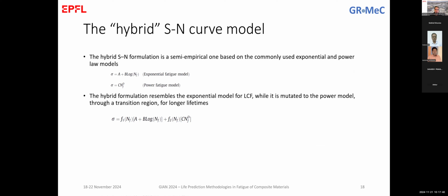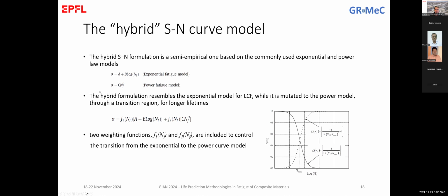low cycle fatigue, the exponential model, when it hits the axis there. So several years ago, we suggested a model that is a mix of these two. We call it a hybrid model. And actually, we introduced two weighting functions that are factoring the mix. And they change the slope at a certain number of cycles, which we call the transition number of cycles. That is defined in the publication. You will see that it is defined specifically.